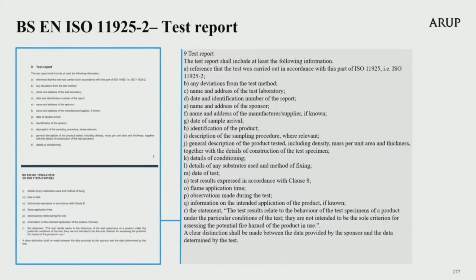The results of the test shall be expressed by a record of the following: the position of flame application, whether ignition occurs, whether the flame tip reaches 150 millimetres above the flame application point, and the time at which this occurs. Presence of flaming droplets or particles which cause ignition of the filter paper, and observations of physical behaviour of the test specimen. Again, the test report has to include a general description of product tested, the form of construction of the specimen, including the description of substrate used and methods of fixing. This test also requires information on the intended application of the product, if known. And it contains the same statement again.